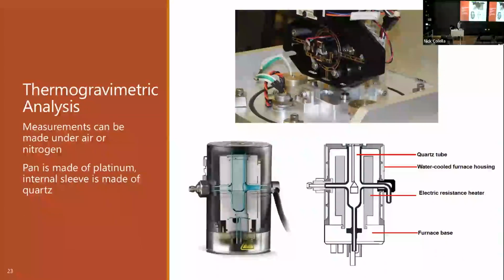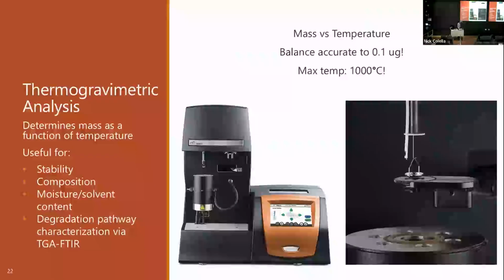A little bit about the internals of the TGA. So this is the fancy balance inside. So there's actually a reference pan in here, and it's a traditional balance, 2 arms. So we have our sample pan here. You'd load typically about 5 milligrams of sample in, and then heat it up.